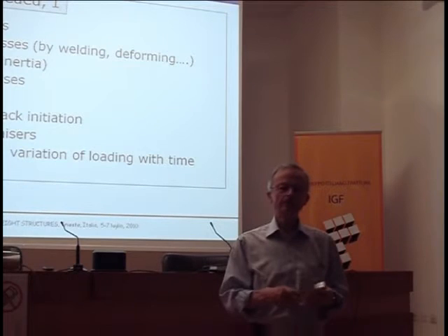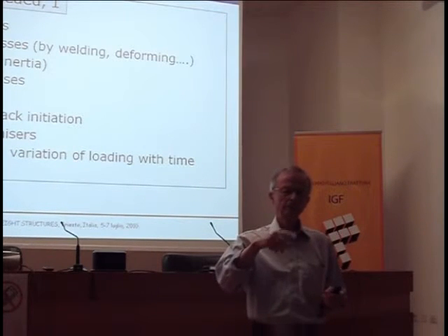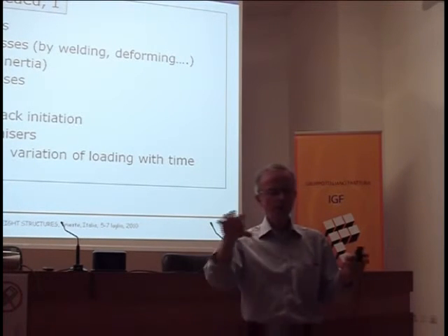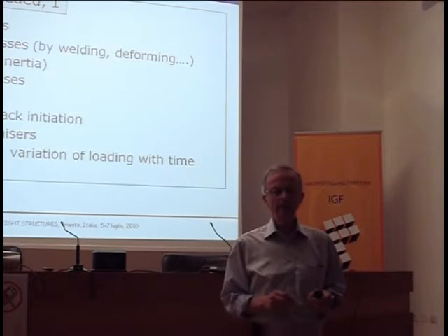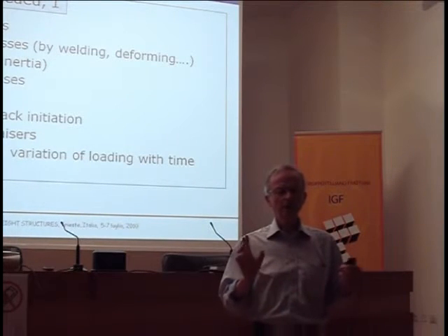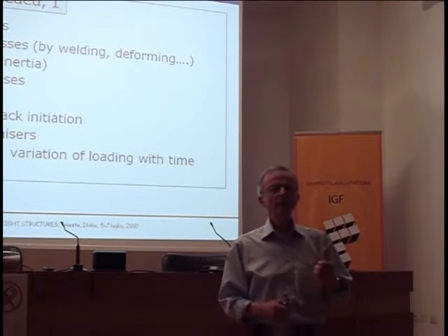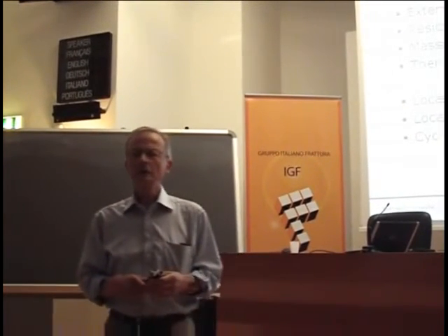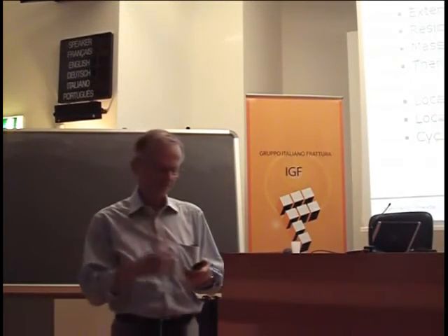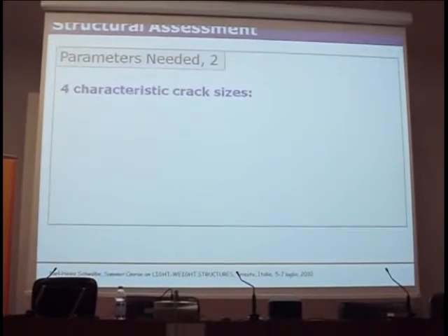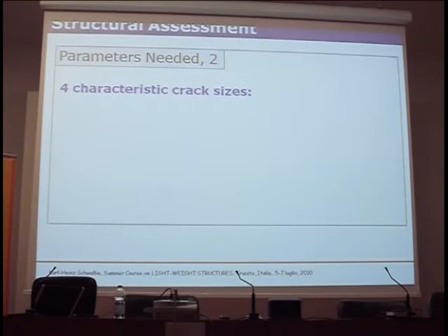And then we have a stress distribution for a flight from takeoff till landing. And this is then carefully studied, and then people say, this is one load cycle, composed of whatever. And each flight is a load cycle, and 1,000 flights mean 1,000 load cycles. So it makes testing and calculation easier.